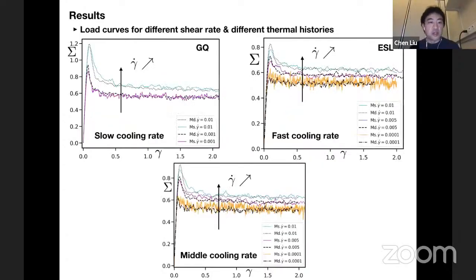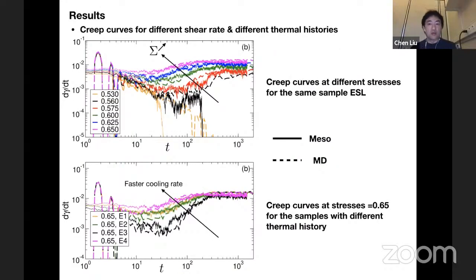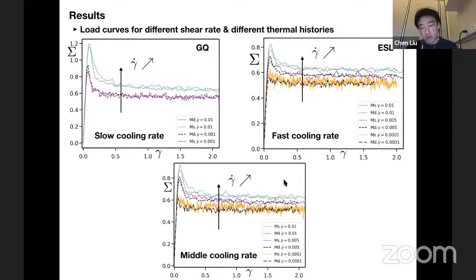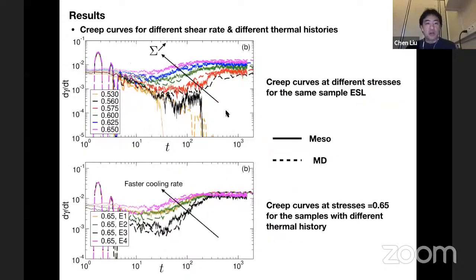And then we apply this coarse-graining length scale to different samples with different thermal histories. From the left, this one has the slowest cooling rate that we have, and to this one we have the fastest cooling rate. You can see that for different shear rates, the meso data captures relatively well the transient behavior up to the stationary plateau. And what is quite surprising to us when we did the work is that once we fix the parameters for the stationary state and for the transient behavior of shear startup, the creep curves are automatically fixed also.